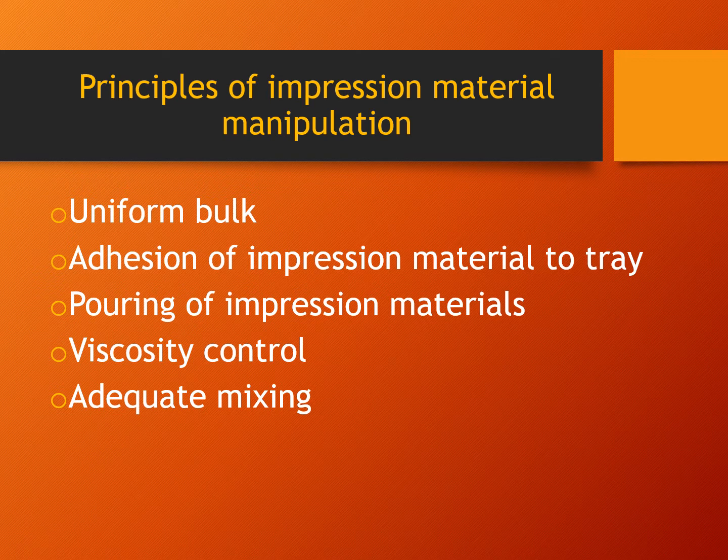polymerization shrinkage. So the optimum method of impression making is to use a low viscosity material to capture the fine details of the prepared margin, grooves, etc. And the bulk of the impression should be made with high viscosity material. For this, the heavy body material helps. They push the light body material into the gingival sulcus and result in minimum distortion due to polymerization shrinkage.